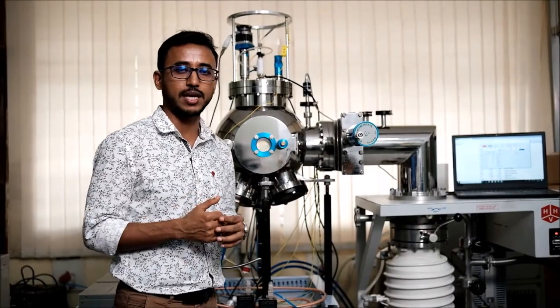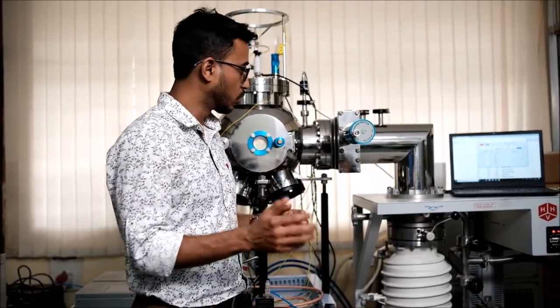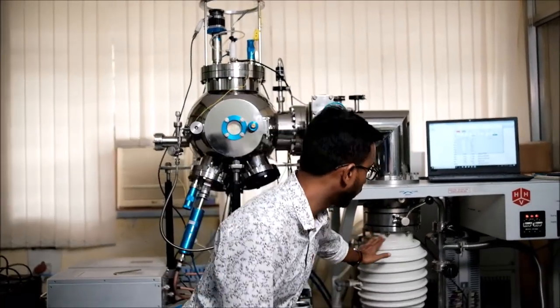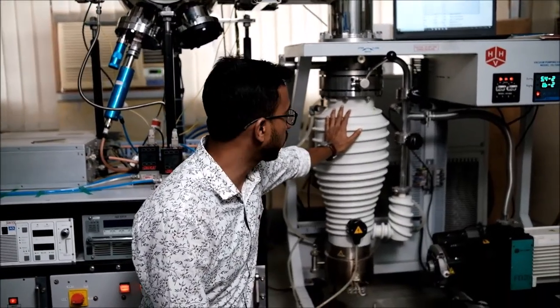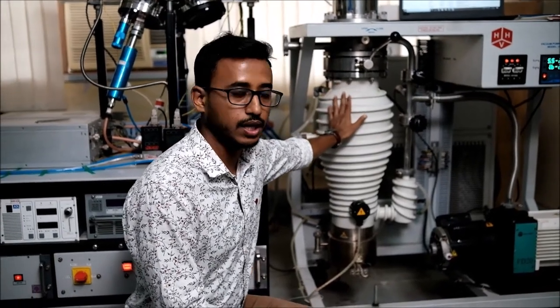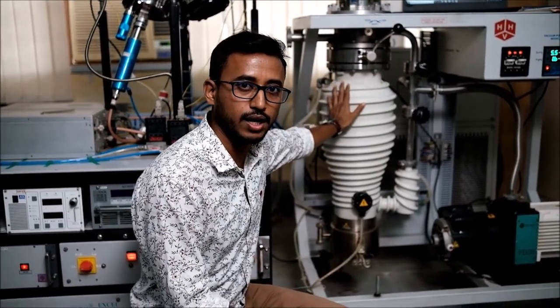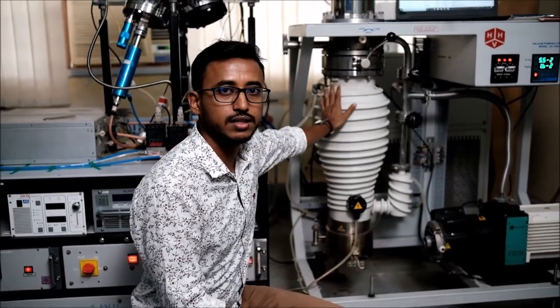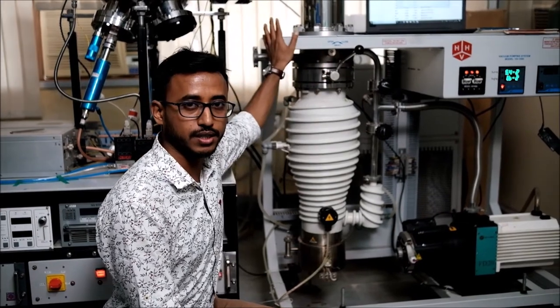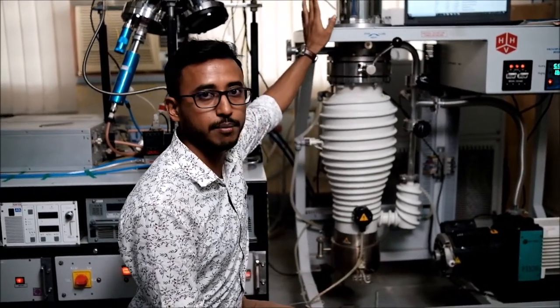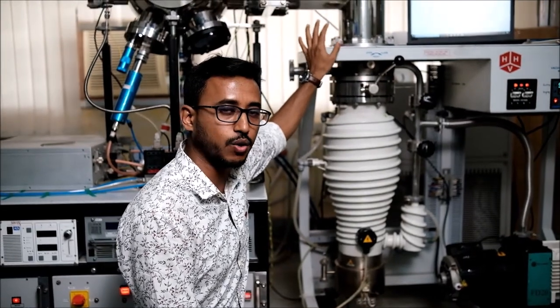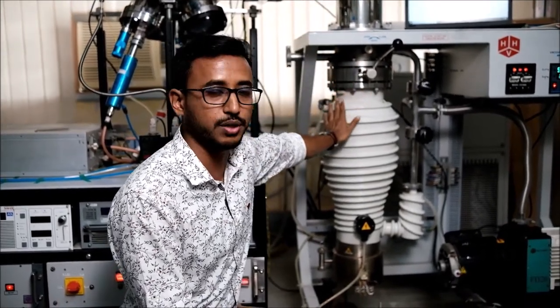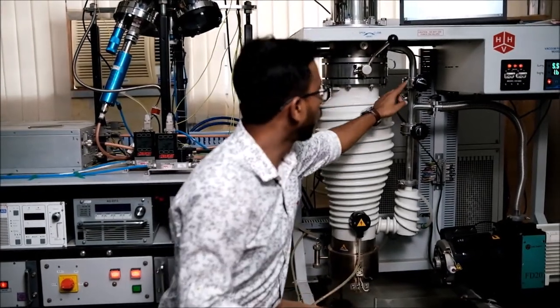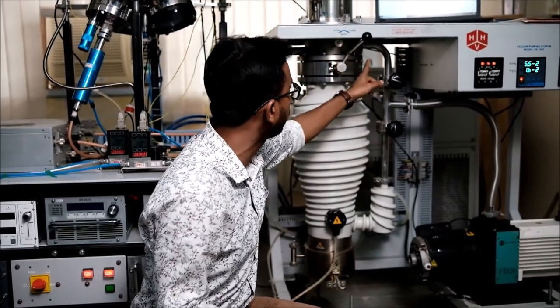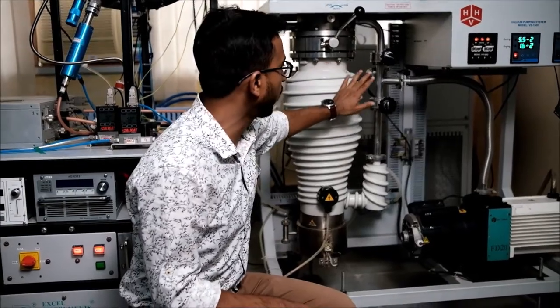I would also like to share some of the precautions we have to take when using the diffusion pump. As we know, we heat up the diffusion pump oil, we should not heat it up without evacuating the chamber. And also after heating up the diffusion pump oil, we should not connect this diffusion pump directly to atmospheric pressure. That means only after evacuating the chamber to 10 to the power minus 3 millibar pressure, we can connect this chamber to the diffusion pump chamber. And also we should not open this roughing and vacuum valve at the same time. Then the gas from the chamber can directly come to the diffusion pump chamber. So we should avoid this.